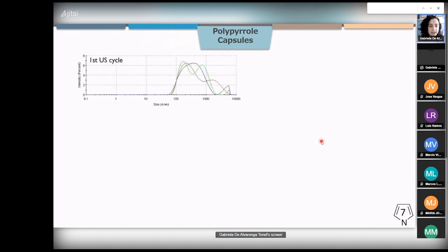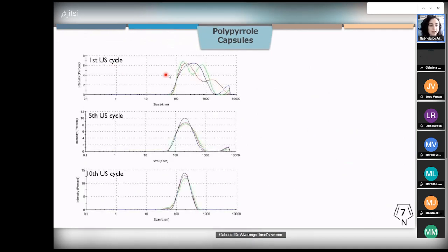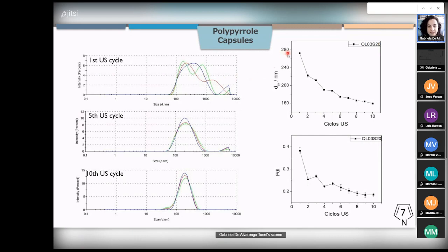So for the polypyrrole capsules, we first analyzed how many ultrasound cycles were enough for us to reach the nanoscale. So we determined that with 10 cycles of ultrasonication, 10 cycles of 1 minute, we could reach sizes around 160 nanometers and a low polydispersity of the oil droplets, below 0.2.